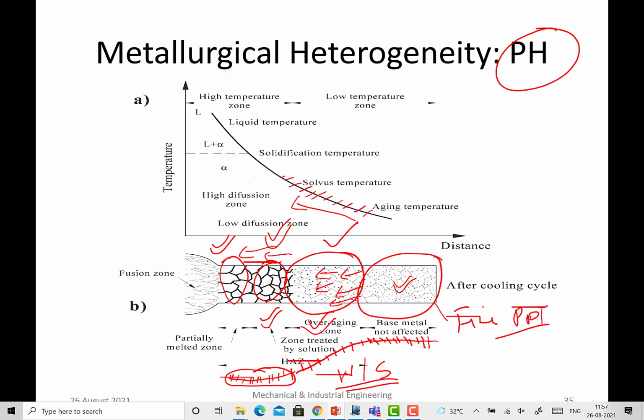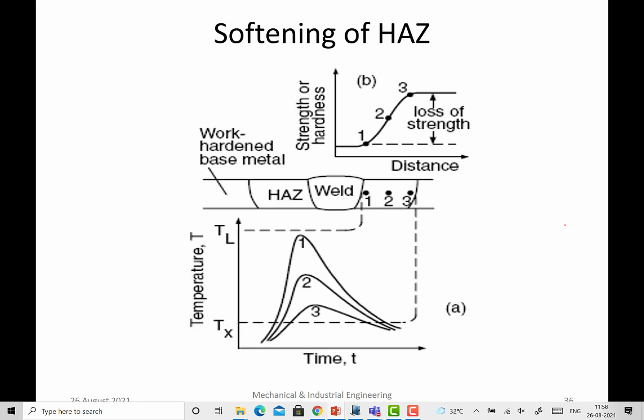Okay, in order to restore the property similar to the base metal, there are two ways. You go for PWHT. So there are two ways, either you go for T6 kind of condition or T4. Just solutionize and put it under the welding condition. There are naturally aged metals also, like the aluminum, zinc, magnesium alloy. You weld it, after a week or so it will regain its strength. So that is a different thing, but it is not so for 2000 and 6000 series aluminum alloys. Okay. Coming to the grain refinement, those which are strengthened by the grain refinement, you see their story.